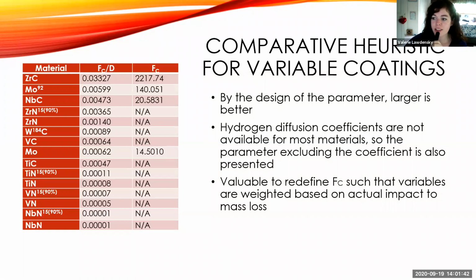And very important here is that a lot of these materials have a number of isotopes, and some of them are very friendly or completely neutral to neutrons, but some of them will absorb them and make reactions harder. That's why I put molybdenum 92 there, because if you enrich out all of the isotopes that really are not helpful and leave it at the one that's really nice, 92, you get a good job. As opposed to molybdenum as it is, about halfway down the table. But this is simply a basis for what future experiments and studies would be useful for other coatings.